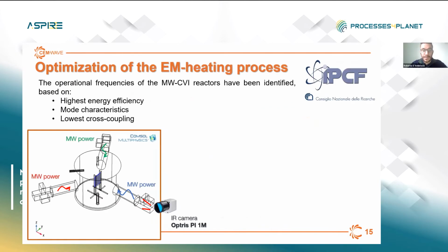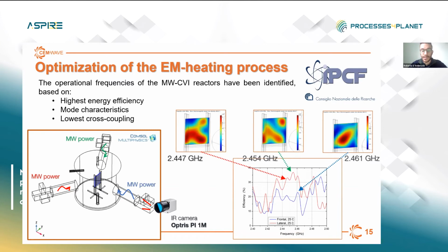Another major advantage coming from the application of this new technology derives from the solution of the coupled electromagnetic thermal problem by a rigorous numerical modeling, which has been carried out by the Institute of Physico-Chemical Processes in Pisa. In this way, the most efficient operational conditions can be identified in terms of the resulting operating frequencies, which have been chosen following three different criteria, which are the achievement of the highest energy efficiency in terms of energy deposited in the sample, the selection of modes with electromagnetic field distribution suitable for the application of interest, and the minimized cross-coupling level in terms of reflection of power in the other channels, which is inevitable when working with more than one source at the same time.